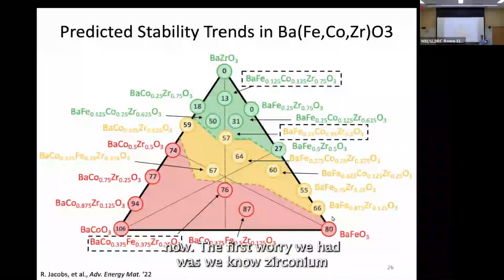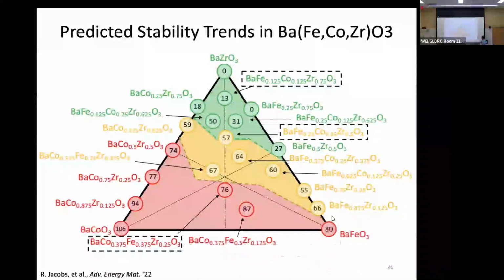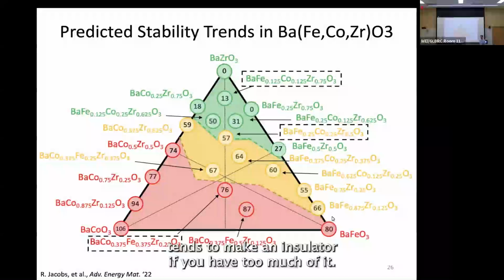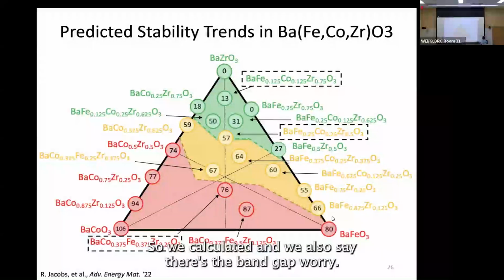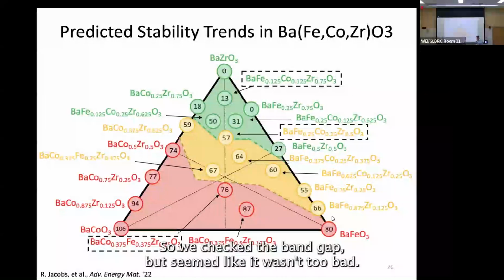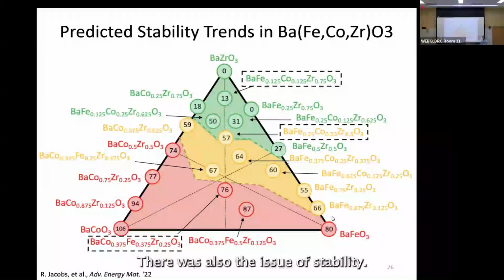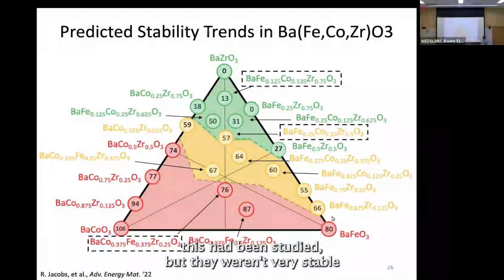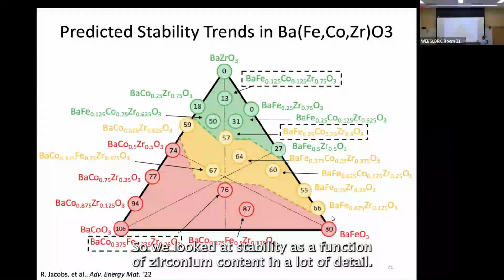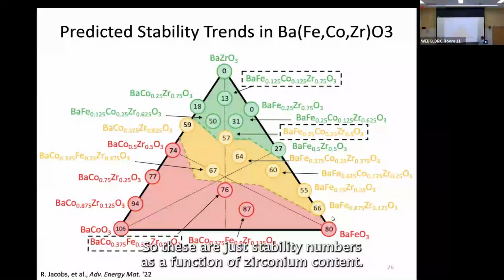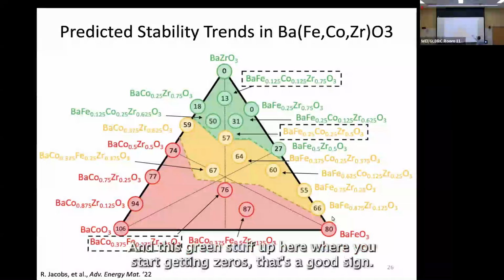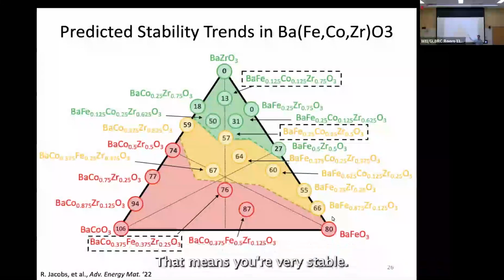Now, the first worry we had was we know zirconium tends to make an insulator if you have too much of it. So we calculated, and there's the band gap worry. So we checked the band gap, but it seemed like it wasn't too bad. There was also the issue of stability. A lot of these compounds that were similar to this had been studied, but they weren't very stable. And we knew that was going to be a problem. So we looked at stability as a function of zirconium content in a lot of detail. These are just stability numbers as a function of zirconium content. And this green stuff up here, where you start getting zeros, that's a good sign. That means you're very stable.